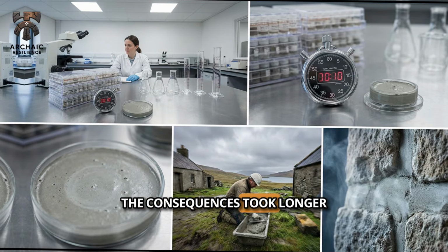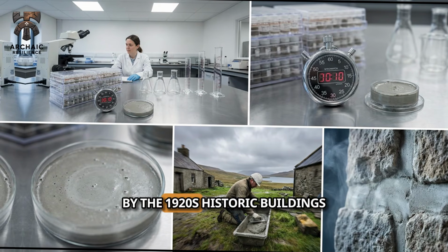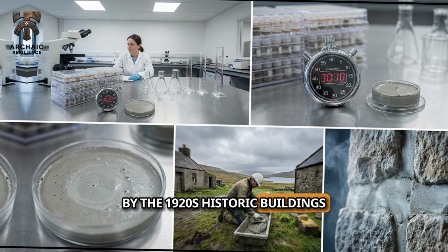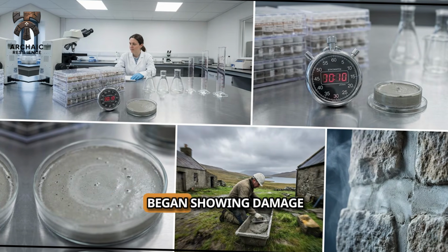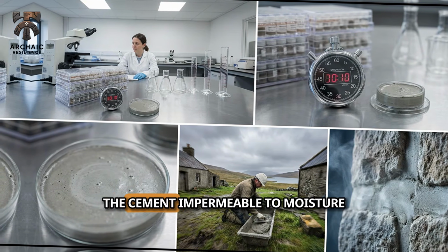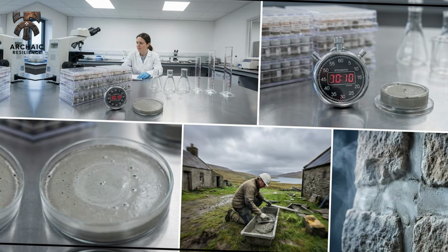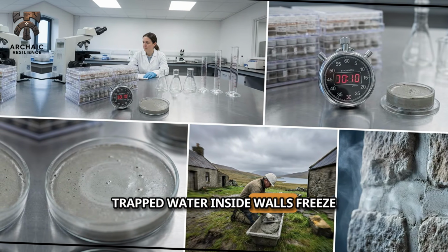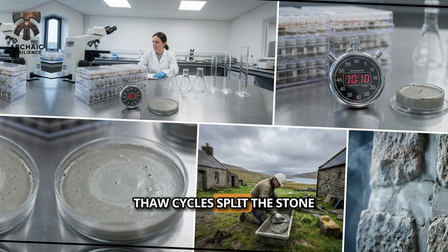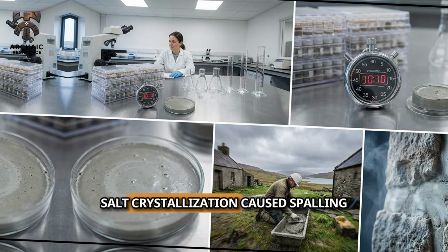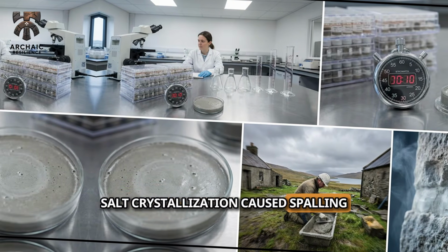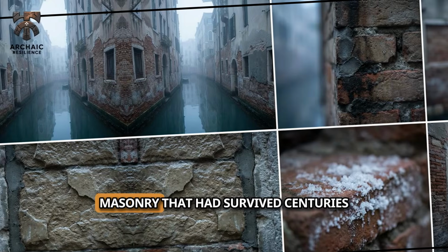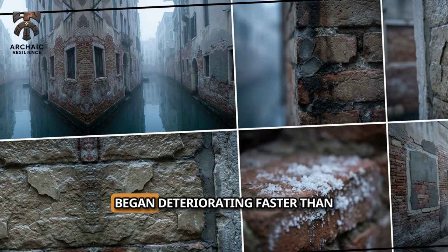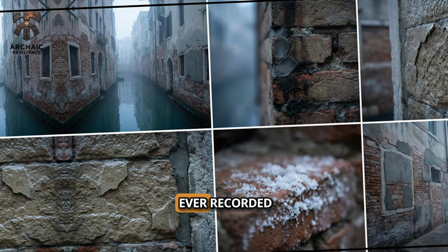The consequences took longer to appear. By the 1920s, historic buildings repointed with Portland cement began showing damage. The cement, impermeable to moisture, trapped water inside walls. Freeze-thaw cycles split the stone. Salt crystallization caused spalling. Within decades, masonry that had survived centuries began deteriorating faster than ever recorded.